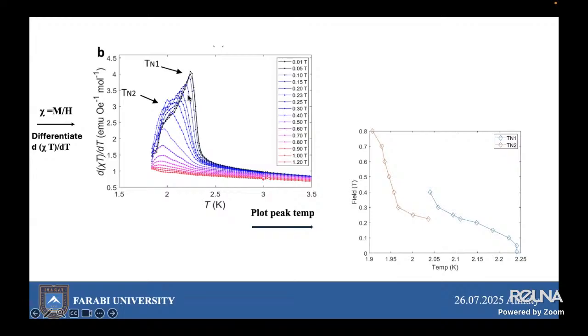Both transition lines show a decreasing trend with increasing magnetic field, which suggests that the applied magnetic field suppresses the magnetic ordering. The second magnetic transition vanishes above about 0.3 Tesla, indicating that this lower temperature phase is fragile in a magnetic field. The first magnetic transition persists up to about 0.4 Tesla and beyond, and it also shifts significantly. This phase diagram indicates field-induced suppression of antiferromagnetic phases and helps identify boundaries between magnetically ordered and disordered states.